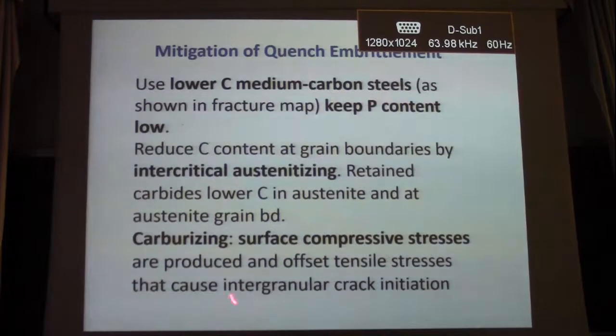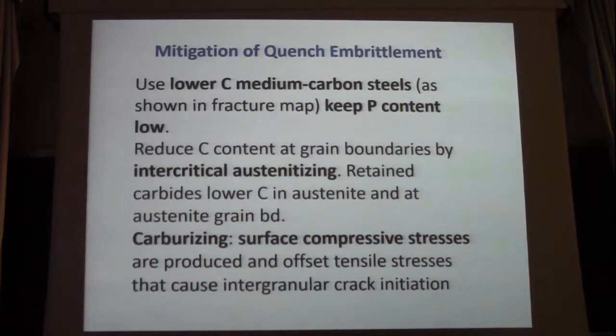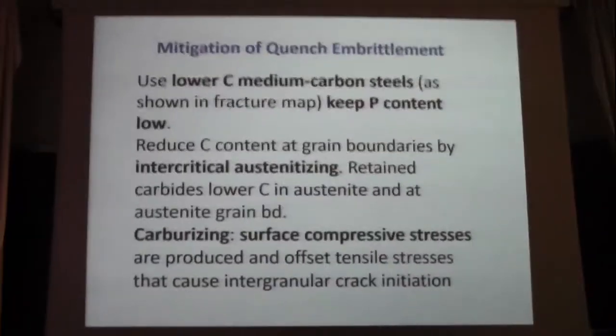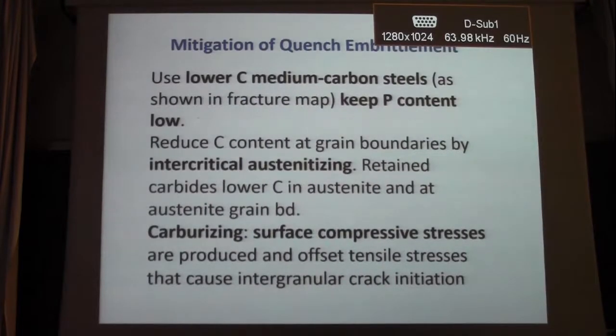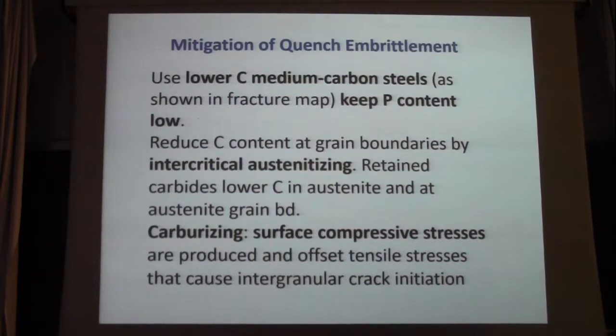Carburizing. Why does it work? Carburizing introduces 0.7, 0.8, 0.9% carbon. And it is because surface compressive stresses are introduced during the quenching of the carburized steels. So I will illustrate those.